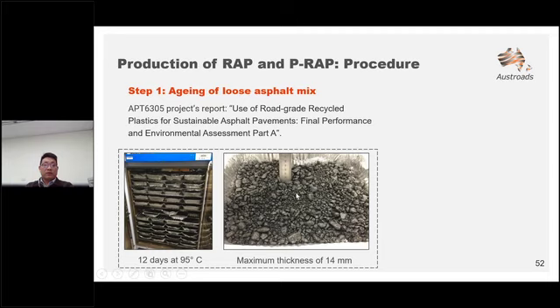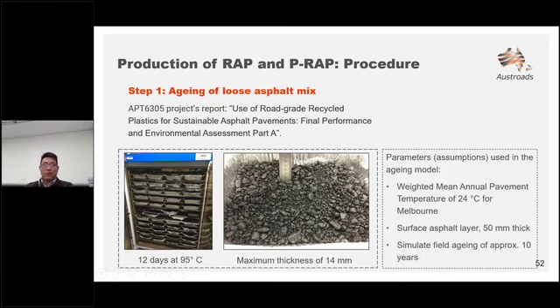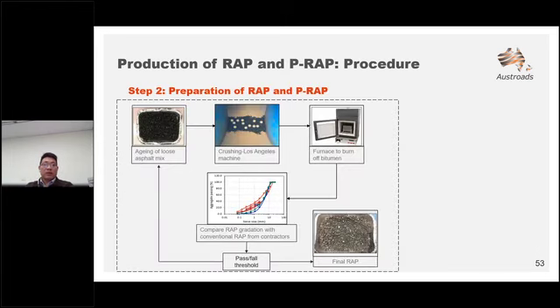To allow homogeneous aging, the maximum thickness of the loose mix in a tray was kept at 14 mm, which is the nominal maximum aggregate size of AC14. The assumptions used to determine the time and temperature include the weighted mean annual pavement temperature of 24 degrees Celsius for Melbourne, the surface asphalt layer of 50 mm thickness, and simulating field aging of approximately 10 years.